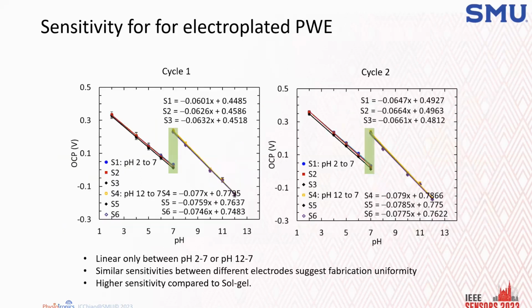However, when we compare the sensitivity, we found something very interesting: although the slopes are roughly the same, when one device goes from acid and one device from alkaline, they do not meet in the middle. At 7, these 2 devices perform differently. We believe that is because when the cycle starts with acid, it is changing the oxide state on the electrode surface. And when they go from alkaline back to 7, the hydroxide is changing the surface. Therefore, when they meet at 7, they have a potential jump.